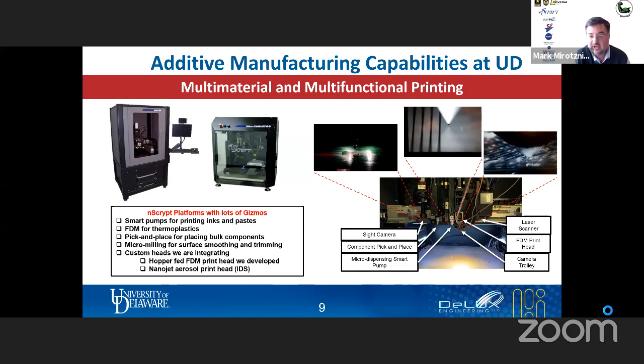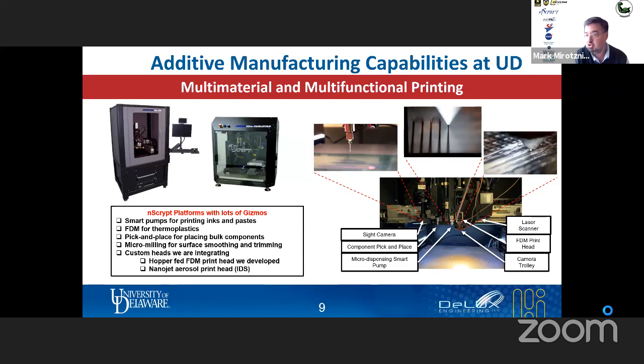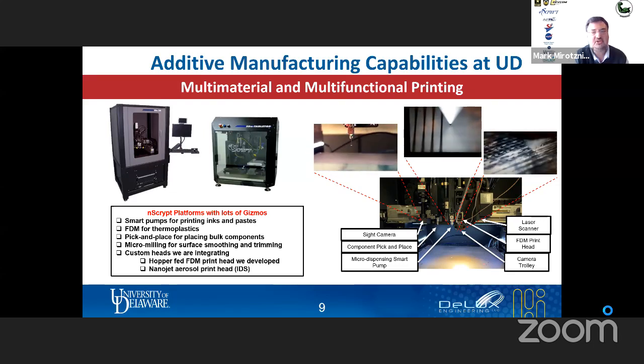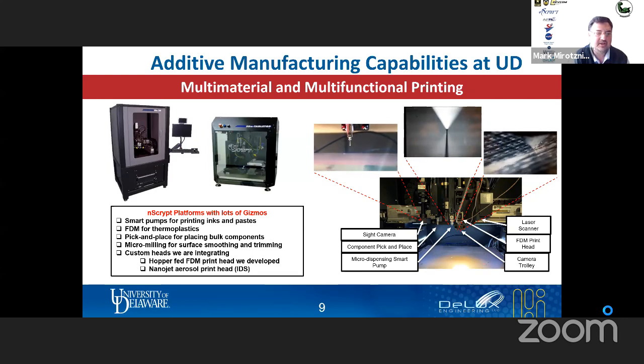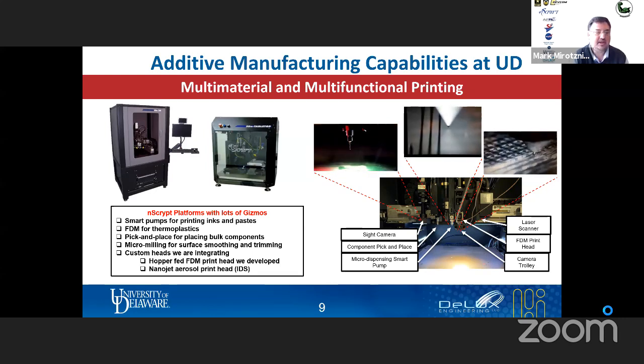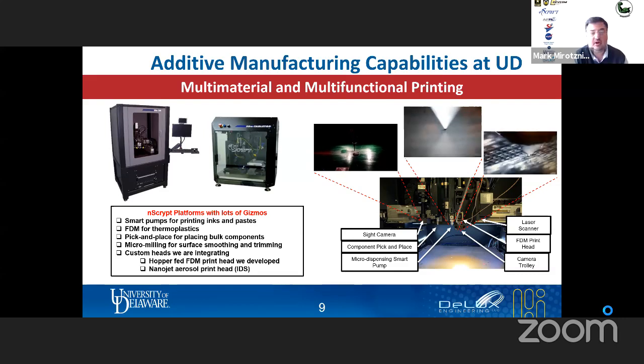So our particular nScrypt, we have a range of gizmos, smart pumps that we print our own, as well as commercial inks and pastes. FDM of thermoplastics, where again, we print commercial thermoplastics and we make our own filaments where we've loaded them for high or low permittivity or magnetic properties. Pick and place of all electronics. We have a micro milling attachment that we use for smoothing surfaces, and we can get surface roughness down to a few microns. And we have a couple custom heads that we've been able to integrate.